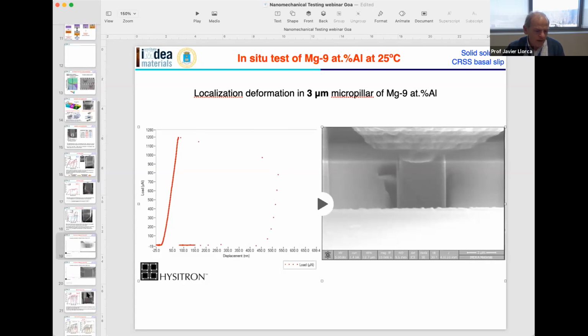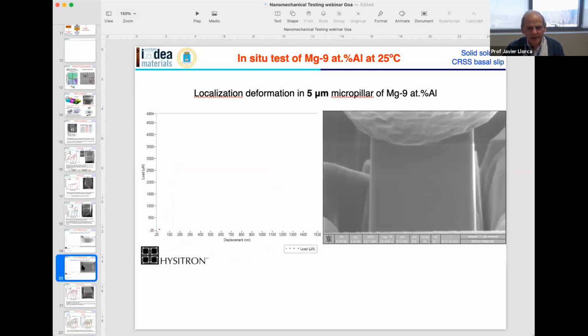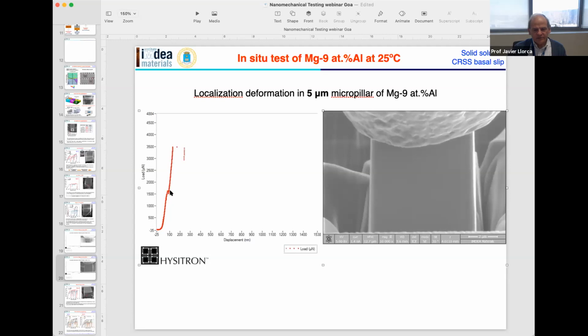If we go to the other micropillar, it's the same material, but in this particular case, the micropillar has dimensions of 5 by 5 microns. You can see that there is a large difference in the deformation mechanisms. Still, you begin deformation with linear deformation, you see a red line. But here at this point, you start to see some pop-ins of plastic deformation.